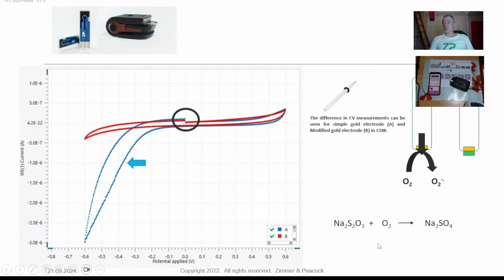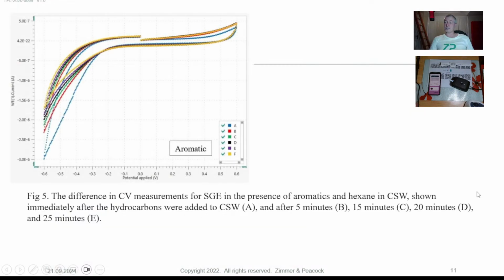When you actually modify the electrode, the blue voltammetry goes away, because I think you're actually blocking the oxygen from getting to that electrode, or for some reason the oxygen concentration is lower at that electrode. It's become significant because it really helps me understand the rest of your voltammetry in a bit. So in this particular case, this is looking at a simple gold electrode. I'm using their terminology here.